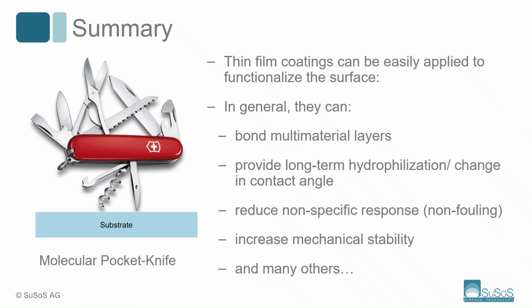So with all that, I hope that I proved to you that thin film coatings, monolayer coatings, can be easily applied to a surface to functionalize it. And in general, they can give us multiple functions: bond multimaterial layers, provide long-term hydrophilization, change the contact angle, reduce the non-specific response, provide no fouling, increase the mechanical stability as we had it for the AAA project, and many others depending on what is needed.